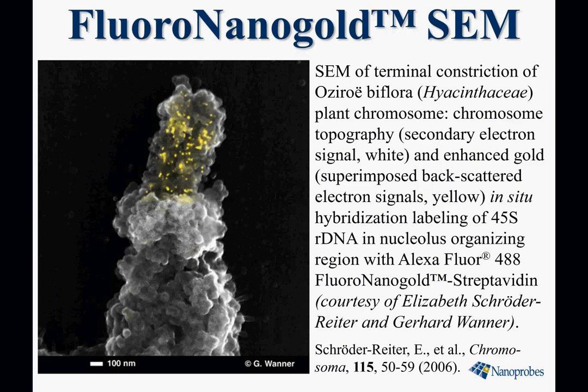Here's FluoroNanogold for SEM. And in this case, what we're looking at is the overlay of the secondary electron signal, which is the regular signal as white is used to visualize, in this case, a plant chromosome with a constriction. And the constriction has been labeled using in situ hybridization with a biotinylated probe detected with Alexa Fluor 488 FluoroNanogold streptavidin, followed by gold enhancement. And the yellow signal is the backscatter signal from the gold, showing the gold nanoparticles labeling precisely over the constriction.